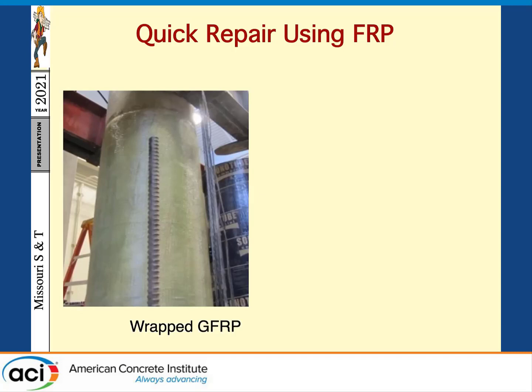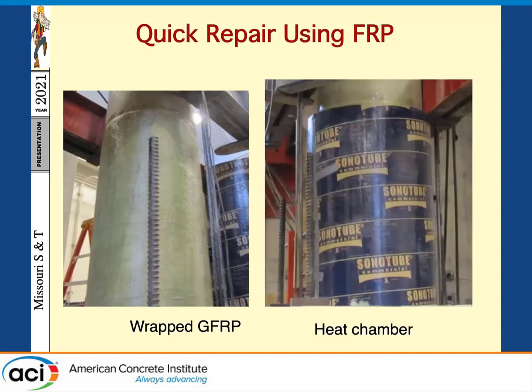So what we did over here, we created what we called a heat chamber. So using the sonotube, we isolated the sonotube from the outside to ensure that it's thermally insulated. And then we have an opening on the sonotube where we apply heat. We used 3 heat guns and applied a high temperature of 50 Celsius, not directly to the FRP, but within the chamber. So the chamber had a constant